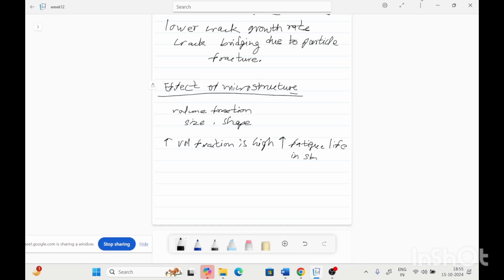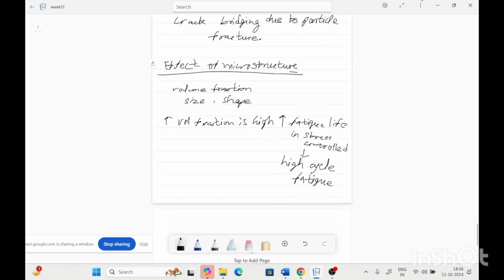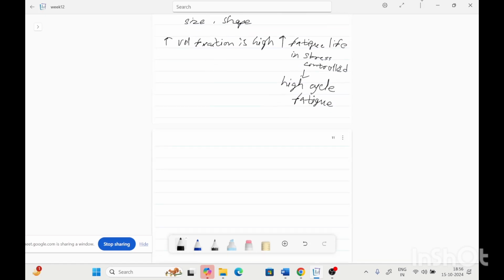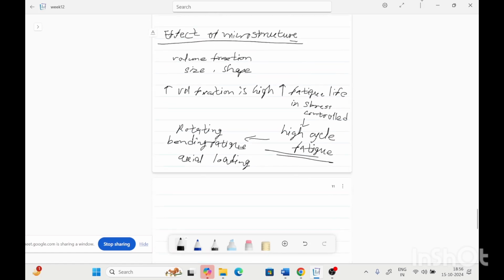So in a stress controlled condition, means high cycle fatigue. So with the increase in volume fraction, the fatigue life will increase in the high cycle fatigue testing. So the high cycle fatigue testing can generally be done on the rotating bending fatigue testing, and the axial loading. And this is the volume fraction effect.